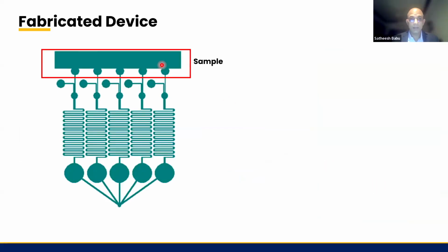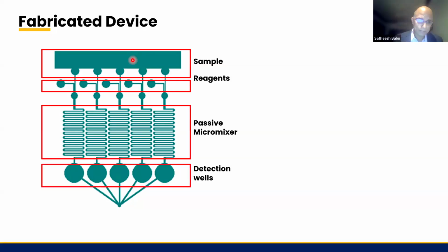So we have a provision for the sample inlet. Then we have the reagents, because when we integrate multiple sensors, all are enzyme-free sensors, and all of them may not work under the same pH as in the blood sample. So we wanted to introduce the reagent with suitable pH and ionic concentration, such that each of these analytes can be detected on an electrode where no enzyme or other biomolecules are integrated. So these are the passive micromixers with an alternately varying diameter of 1:2 that we optimized. Then these are the detection wells. Under these detection wells, we kept the sensor electrodes.